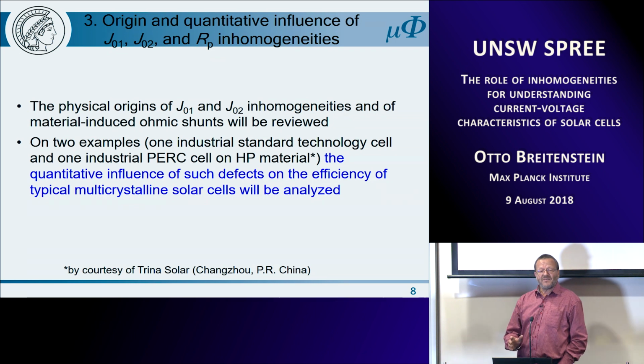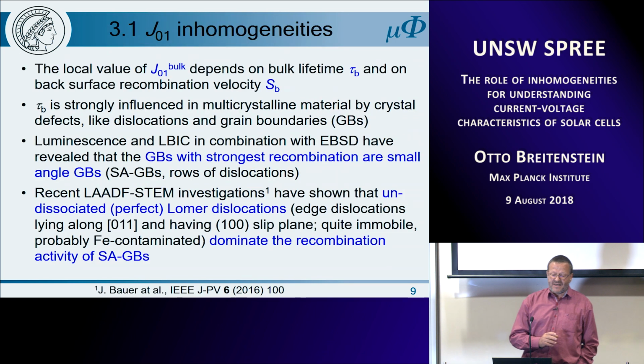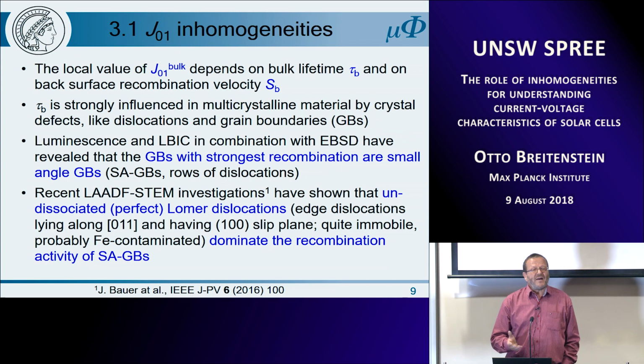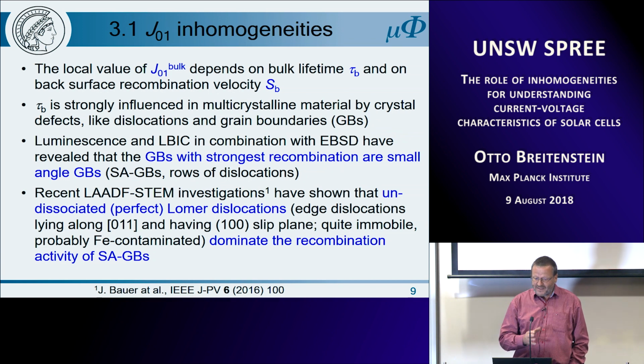So let me start with J01 inhomogeneities. Actually, J01 is, as I've shown already in this little formula at the beginning, the most important solar cell parameter because it determines the open circuit voltage. And the value of J01 depends on the bulk lifetime and on the back surface recombination velocity. And this bulk lifetime is strongly influenced in this multicrystalline material by crystal defects like dislocations and grain boundaries.